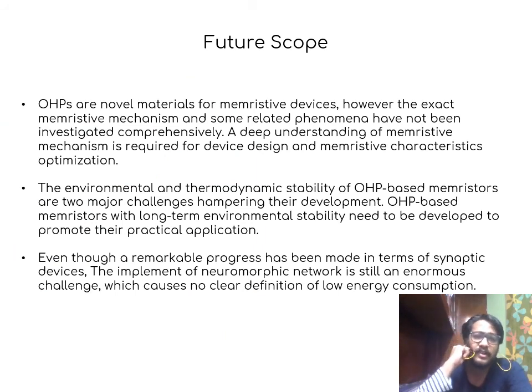While OHPs are great materials for memories, a comprehensive understanding of ion migration mechanism is still a research in progress. OHPs have less stability under humid conditions and a good environmental stability is needed for practical application. Lastly, even though remarkable progress has been made in terms of synaptic devices, the implementation of neuromorphic network is still an enormous challenge which causes no clear definition of low energy consumption.